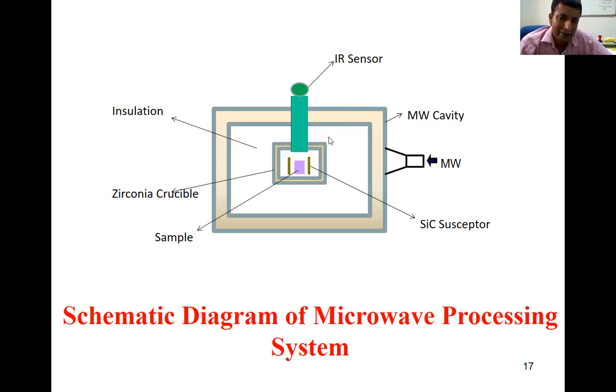The silicon carbide has a limitation: by absorbing microwaves, the temperature it can raise is near about 500 degrees Celsius. Up to that temperature it can supply heat to the specimen, and near about that, reactions start taking place and dipoles start forming in the starting precursors. Then they will start interacting with the microwaves and absorb, the temperature will rise, and more reaction will take place. This is the role of the susceptor I was talking about. But as I told, ideally, if our material is a polar material, then we should not use a susceptor.